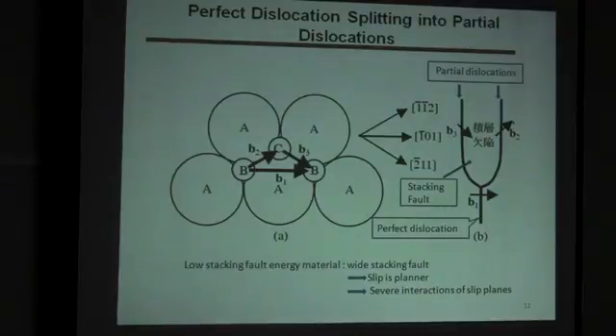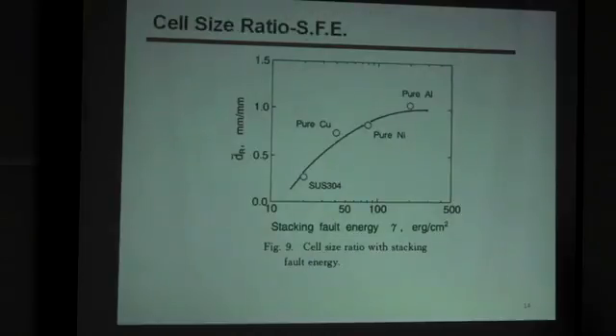And if you give a non-proportional loading, many slip systems interact. So that's the main cause of the large additional hardening in low stacking fault energy material. But in contrast, in high stacking fault energy material, a perfect dislocation remains a perfect dislocation, because the stacking fault energy is very high, so the dislocation energy itself is lower to remain a perfect dislocation. So it will be very easy to make cross-slip. So that's why we find squaring of the grain boundaries and so on. So that's the main cause for the additional hardening.